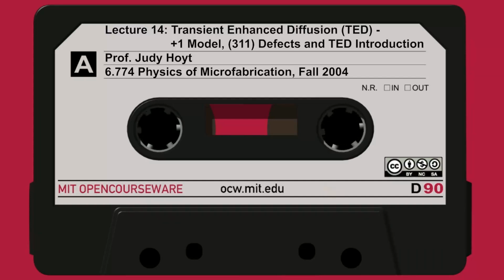You have the dose, you have the Rp, and we know EB, the binding energy, is 1.7, and the migration energy was 1.8. We add all that up, and here is the equation. So this gives us the time dependence for this particular energy and dose. And there it is on slide number 21. This is the duration in seconds of how long TED is going to last for this particular dose and energy of phosphorus as a function of temperature.